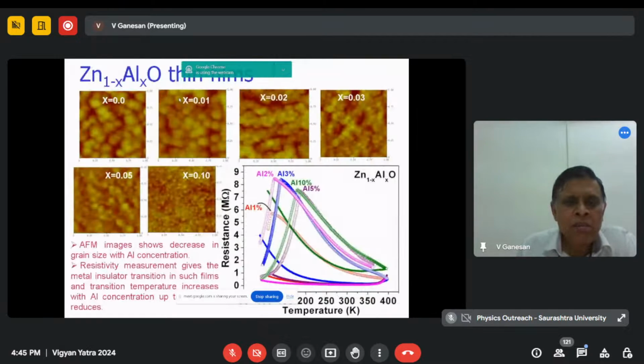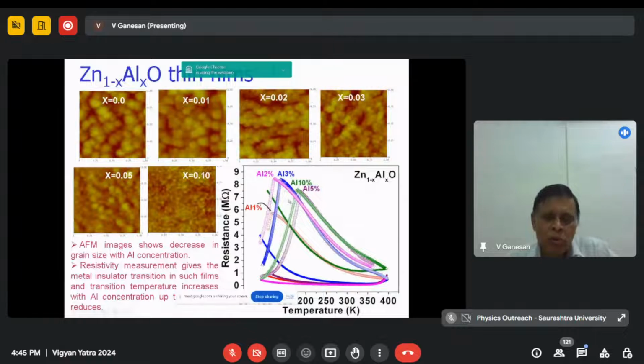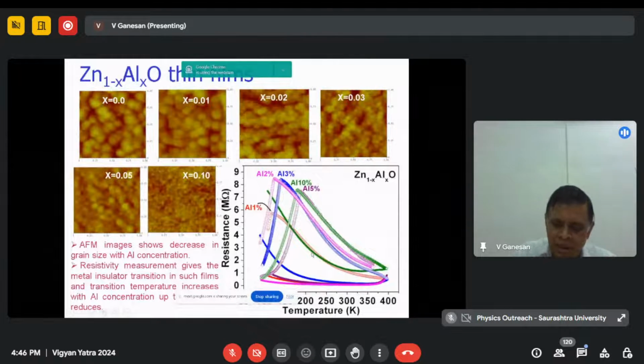So that's that. And then, of course, on zinc oxide, at least 1,000 researchers in India worked on zinc oxide, even now people are doing it. And on various concentrations of aluminum doping, we used to measure resistivity. Then we tried to see the evolution of the grain structures. We can correlate the resistivity, because very important is how to calculate the mean free path as well as localization, for the metal to insulator transition. This is something like localization to delocalization. Anderson localization plays a very interesting role.